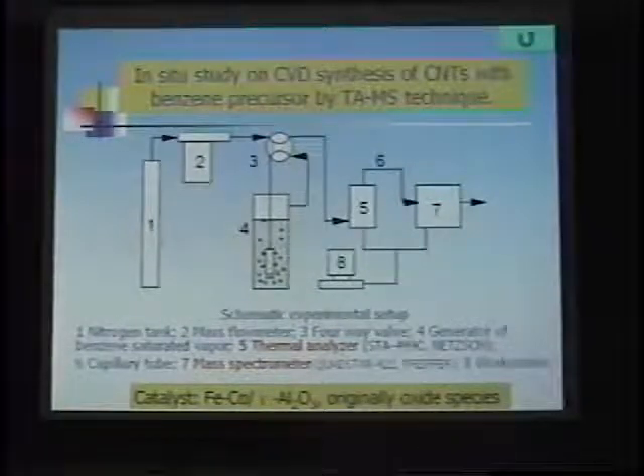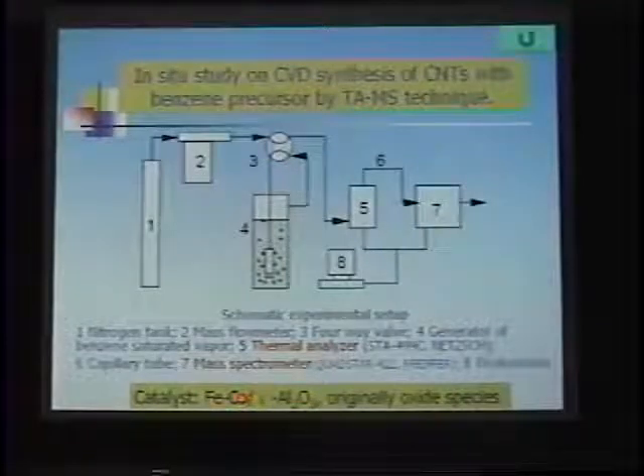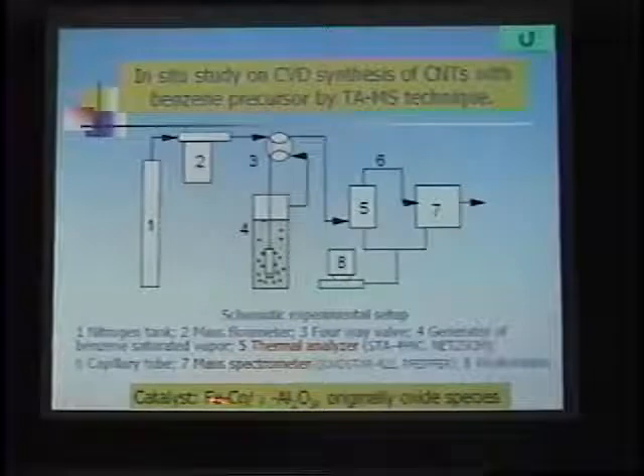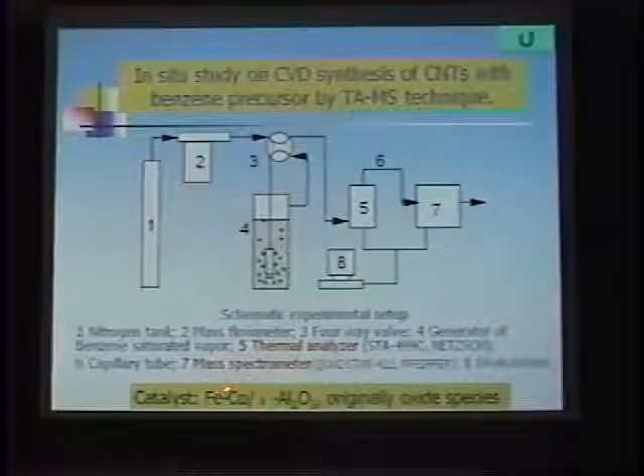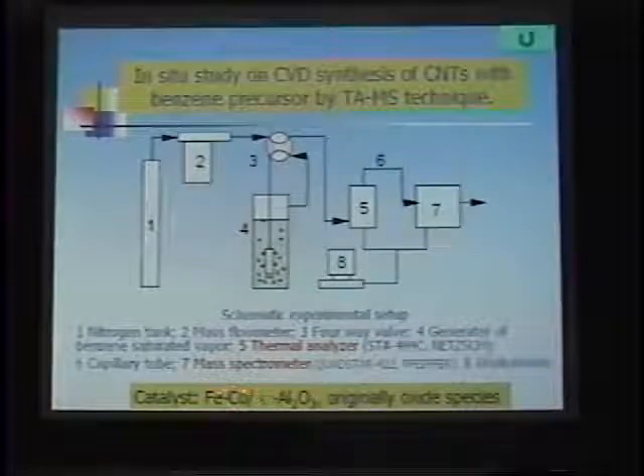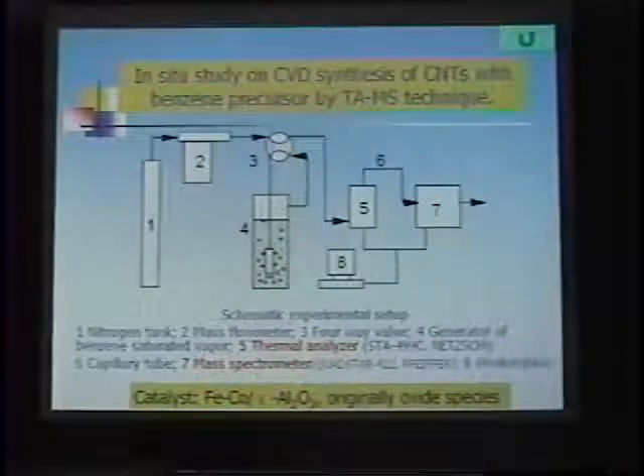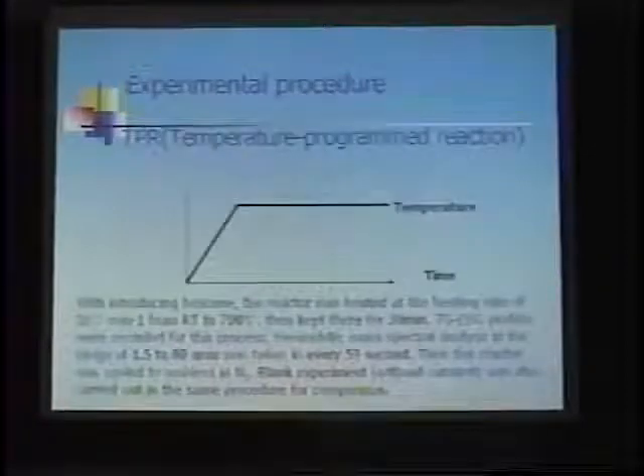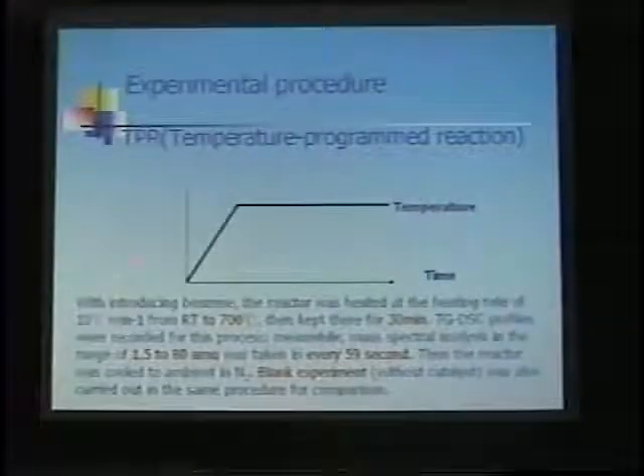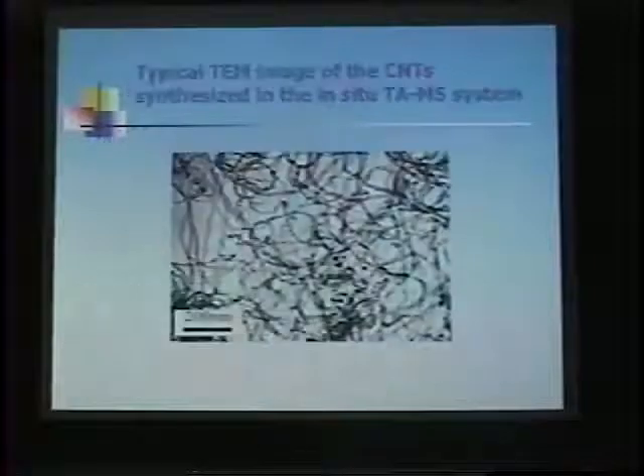Here we use gamma-alumina-supported iron cobalt as the catalyst, and this catalyst was obtained by heating the corresponding nitrate. So originally it is in an oxide state. This is the experimental procedure, and I will not describe it in detail.